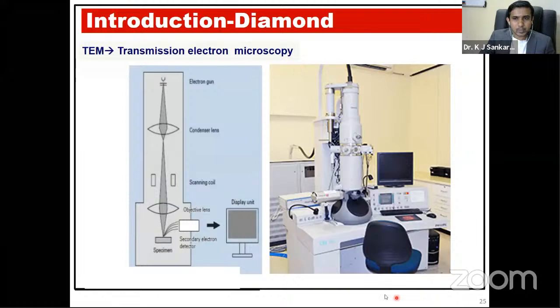This is the transmission electron microscope that I worked with in Taiwan for 2 years. After my PhD, as a postdoc in Taiwan, I was operating this TEM. To get one very good TEM image, you need to spend time, because sample preparation for TEM is a very big job. We can prepare one sample in a week, and characterizing the sample in the TEM is also a big task, because focusing the material to get a very good image is not easy. So we need to spend much time, and need more patience and hard work, to get a single very good image from TEM.